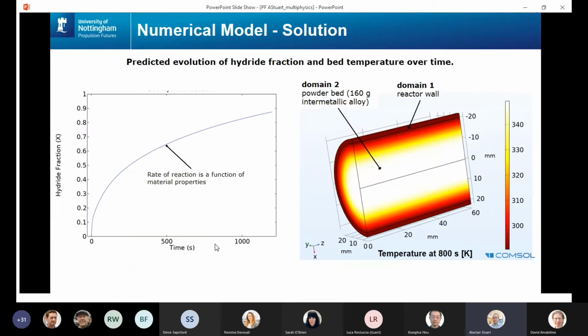I then go on to obtain a solution. You can see on the left-hand side here, the solver has predicted what will happen as the hydrogen transfers into the container. It reacts with the alloy, it becomes bonded with the metal. As it does so, the concentration of hydrogen in the alloy is increasing, and that's this blue curve that I'm showing over time. I've called it hydride fraction, but it's essentially the concentration of hydrogen. And you can see it has a particular shape.